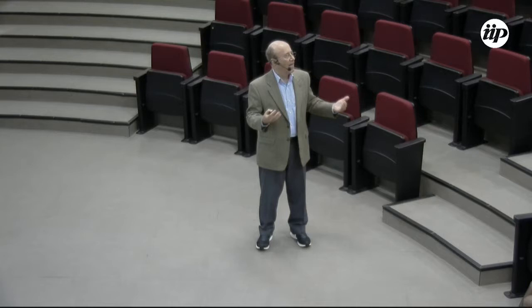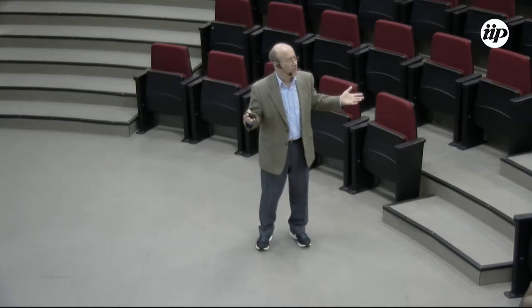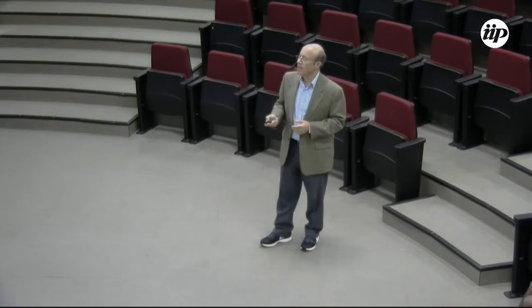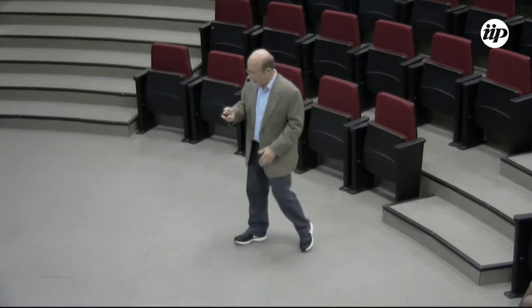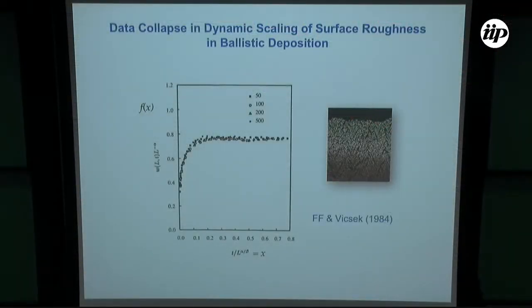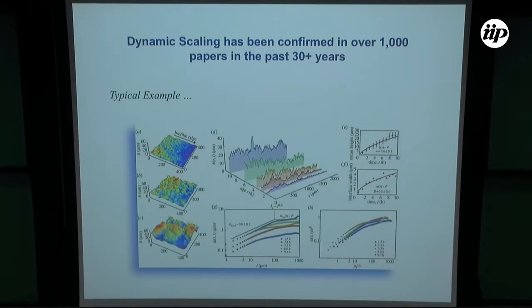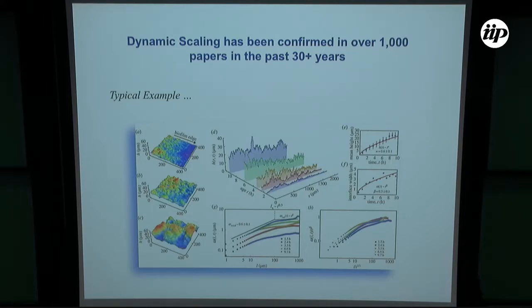You know, until then, the idea that carried over from the Ising model was that people were analyzing them with one correlation length. Nobody thought there could be two correlation lengths, and that was the main contribution here. That actually there are two correlation lengths in this problem, initially f of x grows with the exponent beta as a function of x, and then it saturates like that. Okay, so this is the idea of dynamic scaling that one can use to analyze surface morphology. This idea, since 1984, has been applied to thousands and thousands of different problems, both experimental, theoretical, simulational, and generally it's been an accepted theory, and it has worked in most of the cases, and had been working.